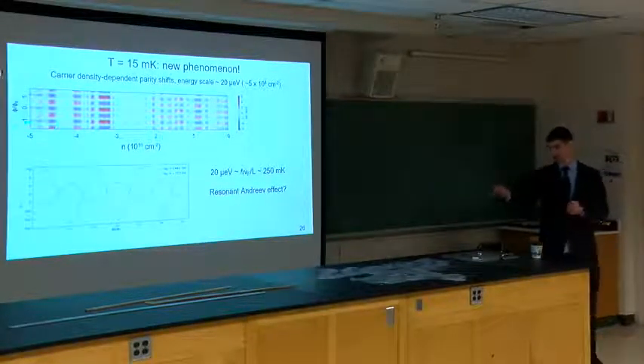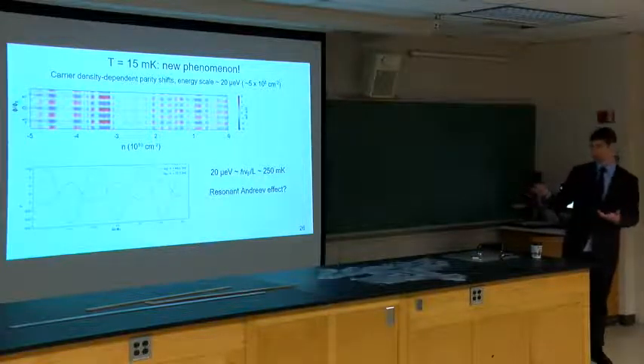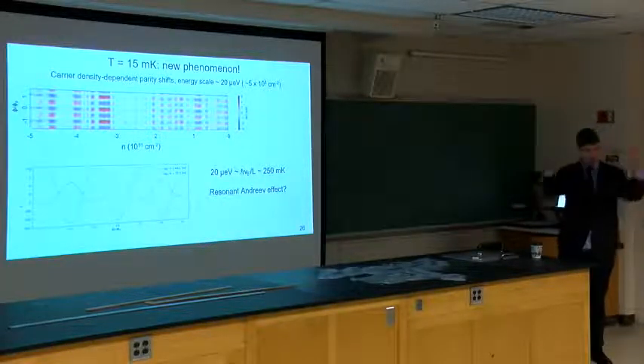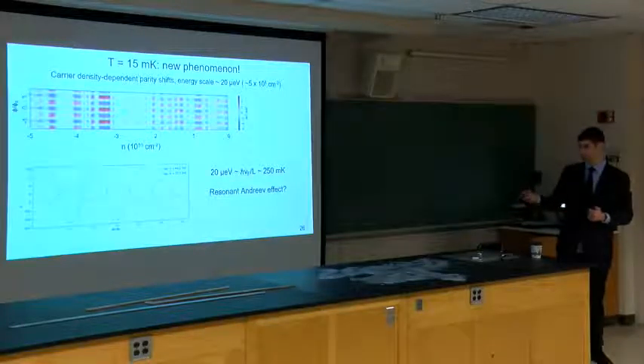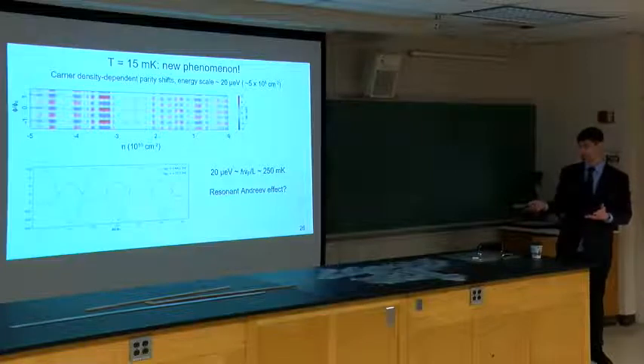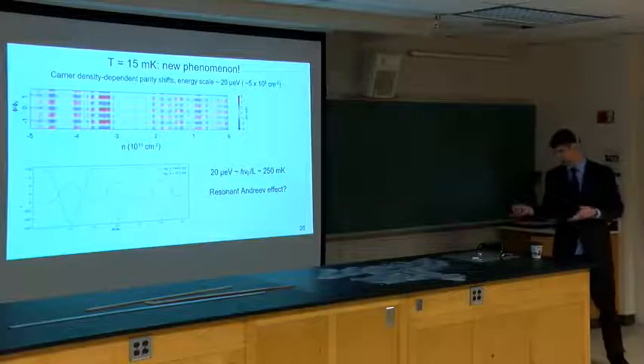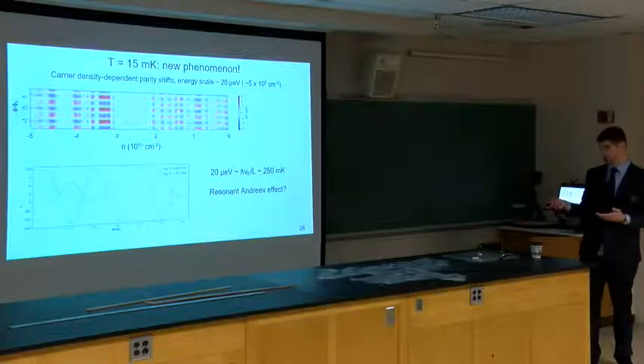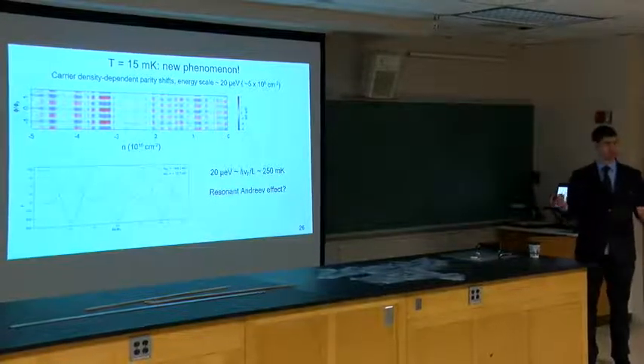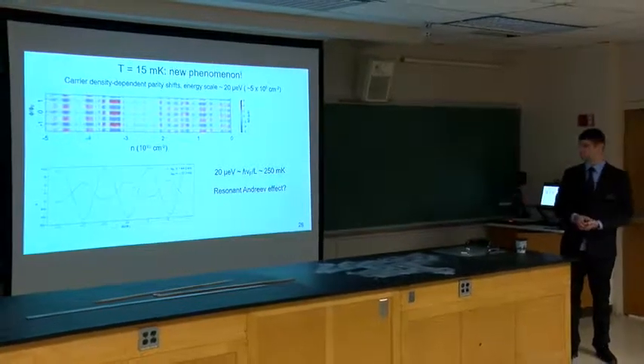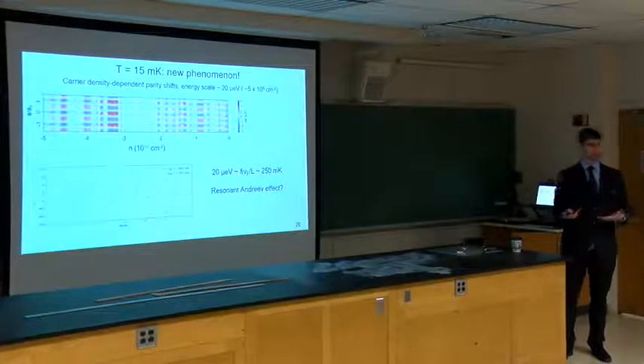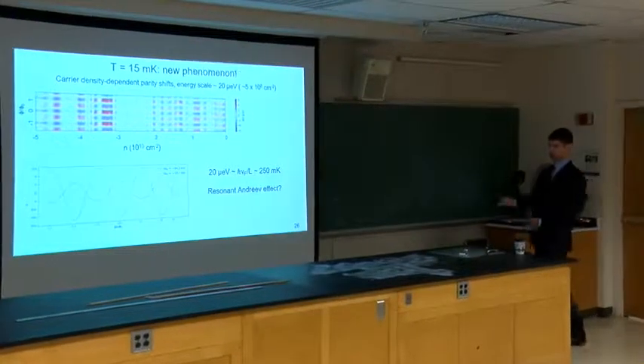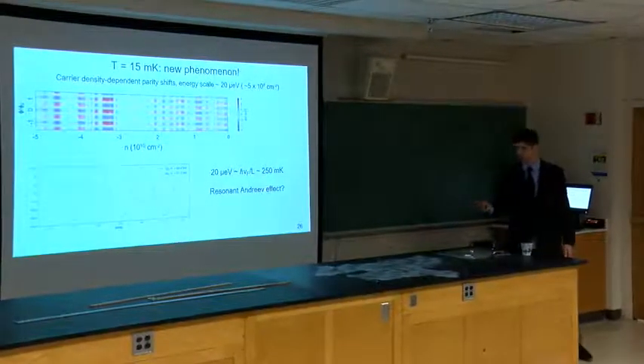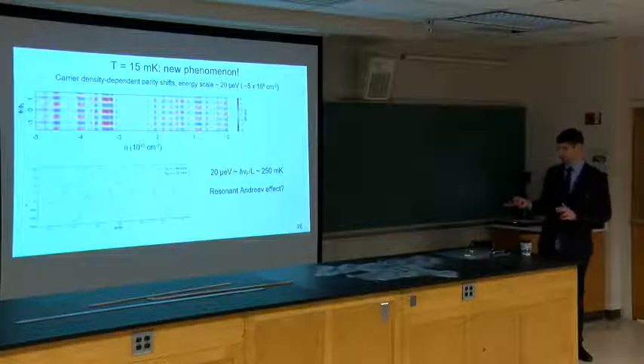So the x-axis here is exactly the same as the previous. This is the magnetic field as per quantum flux for the superconducting loop. We see an oscillation that, again, is sinusoidal, fine, but it flips parity. So we get a pi phase shift as a function of the gate voltage, as a function of charge, which was never really feasible to look at this type of system before. That was interesting.